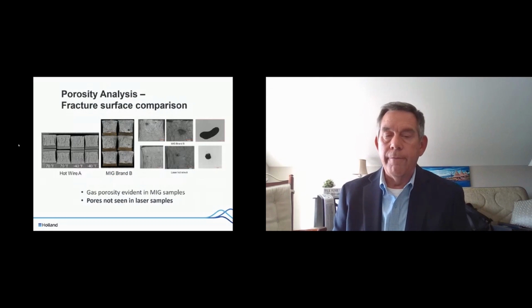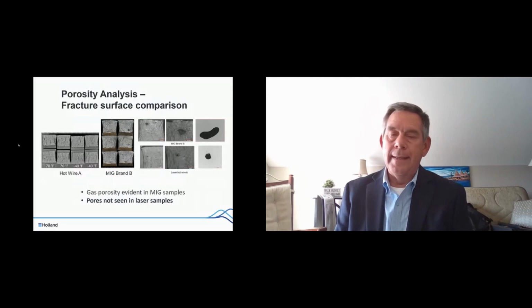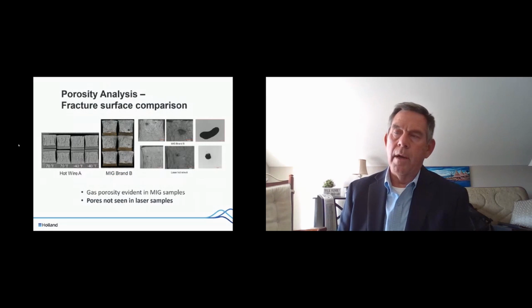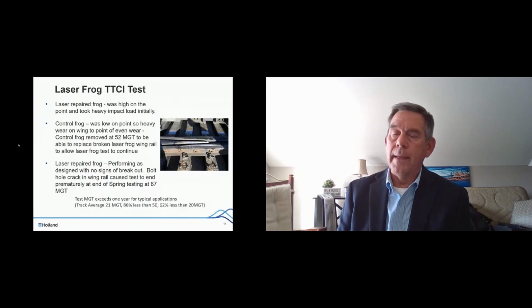The next thing we did in order to validate the process is a side-by-side test at TTCI, the test facility. In this case, we did one repair with MIG welding, and we did one repair with the laser welding, and I ran them. Unfortunately, the test did not last as long as we would like, not because of the material itself or the repair, but because the wing rails broke twice. And so the test was stopped due to that problem.